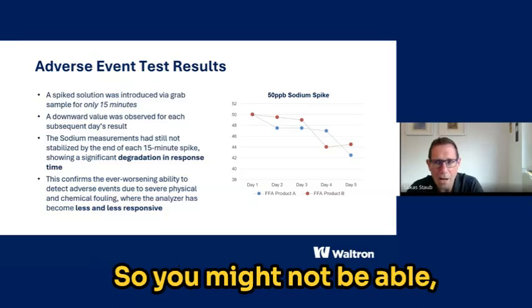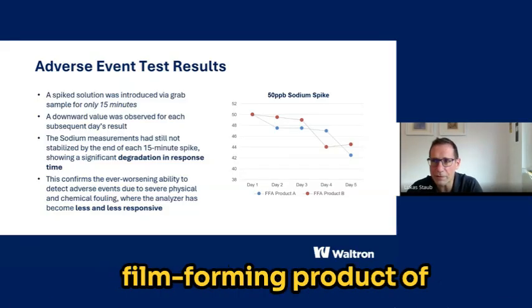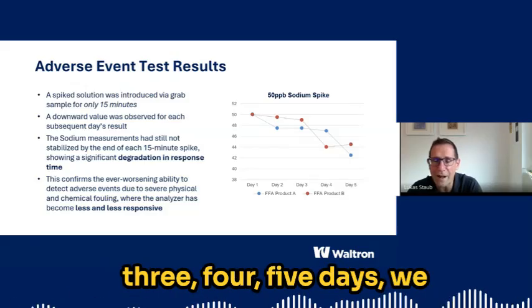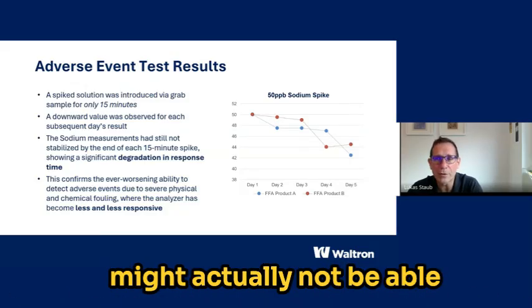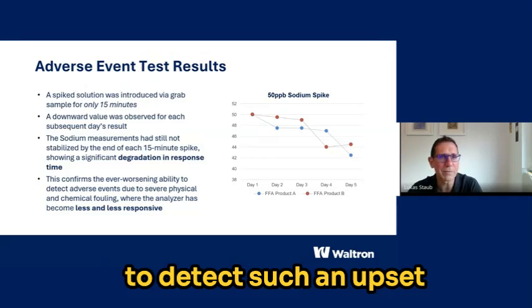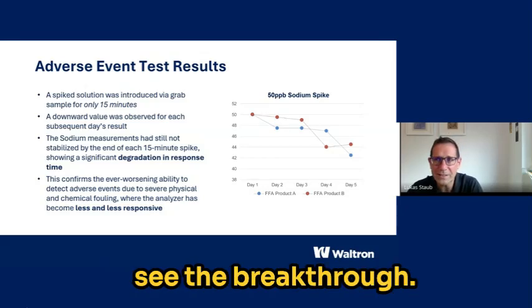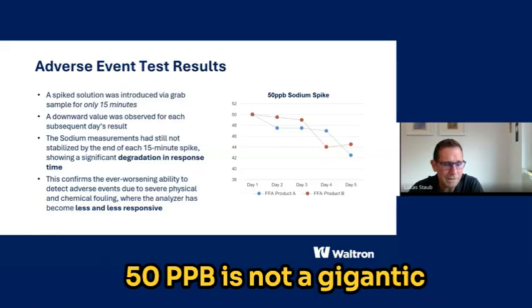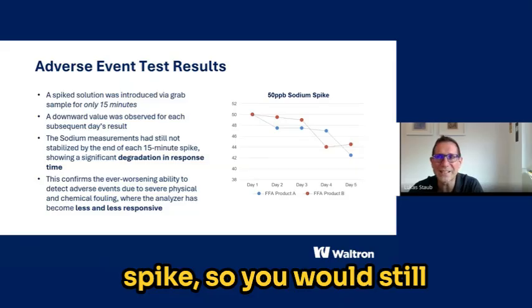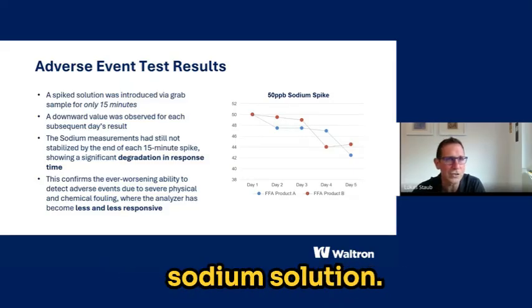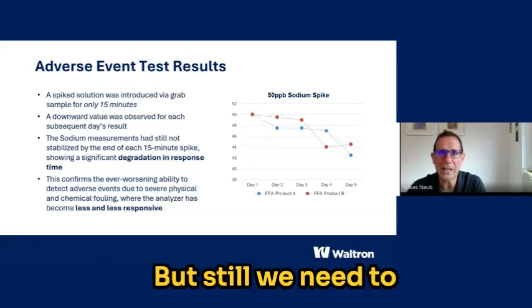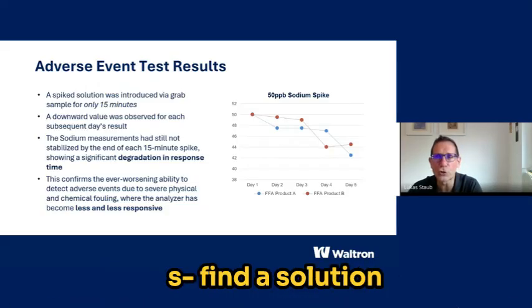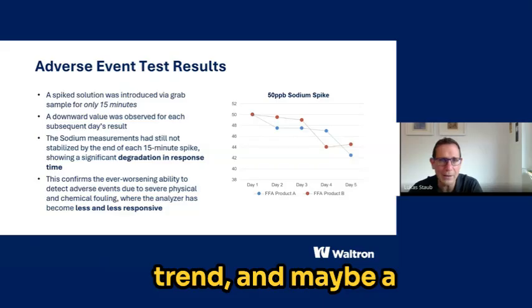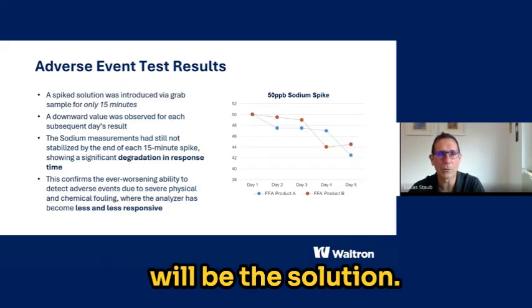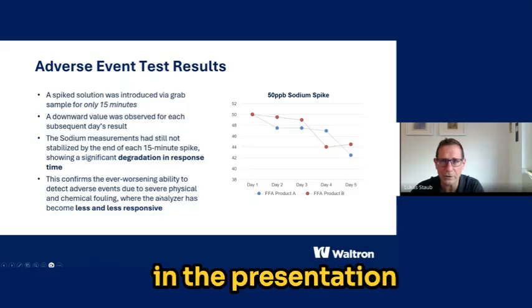So you might not be able, after the application of a film forming product of 3, 4, 5 days, to detect such an upset condition. So we won't see the breakthrough. Though it has to be said, 50 ppb is not a gigantic spike, so you would still see a breakthrough of a higher concentration sodium solution, but still we need to find a solution for this downward trend, and maybe a cleaning or a filtration will be the solution. I'm going to talk about this a little bit later in the presentation.